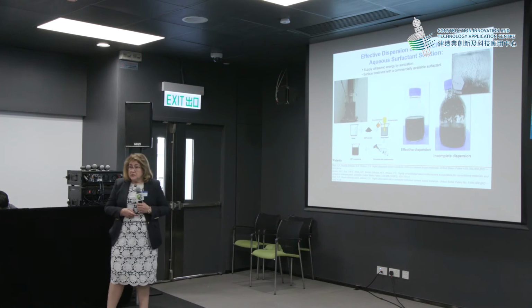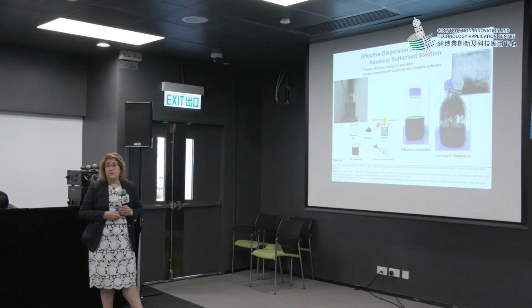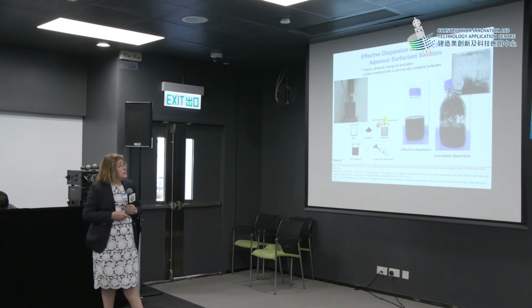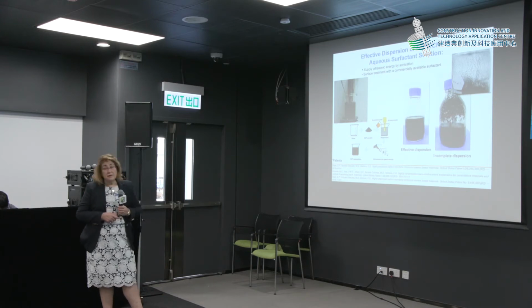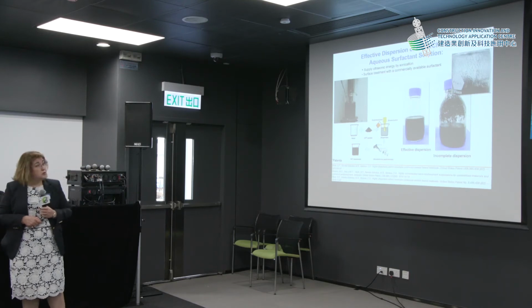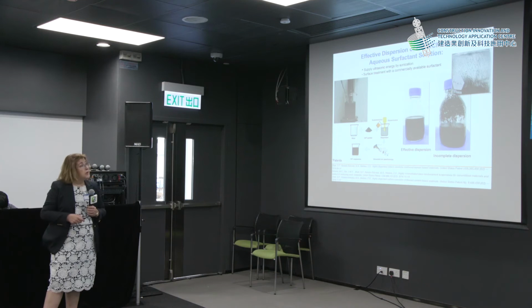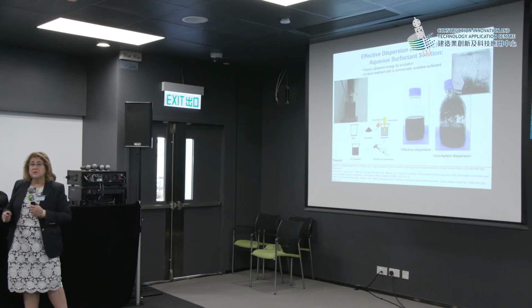examining. A very good dispersion procedure these days is with the use of ultrasonic energy, and the use of ultrasonic energy is by far the best method of dispersing well any nanomaterial that we use, not only carbon nanotubes. And what we want to make sure is that we do not use any surfactants to functionalize the material other than the usual surfactants that we use for concrete.